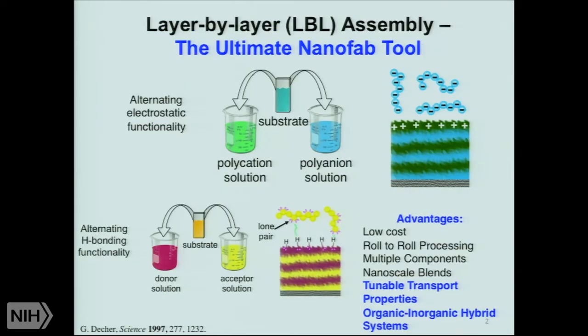This technique is very simple. It involves the alternating adsorption of charged species. Essentially, you can start with a substrate. It can be any substrate, plastic that has been treated so that it has a negative charge, for example, a metal or metal oxide, which has its own native charge. And you can take that substrate and immerse it into a dilute aqueous solution, which contains something that is multiply oppositely charged. Now, when you do that, you're going to get adsorption of that charged polyvalent material onto the surface